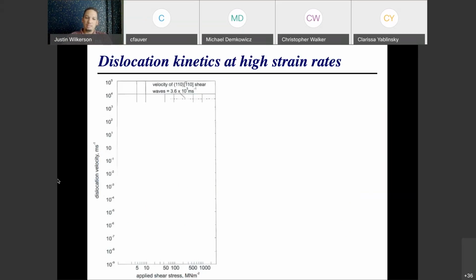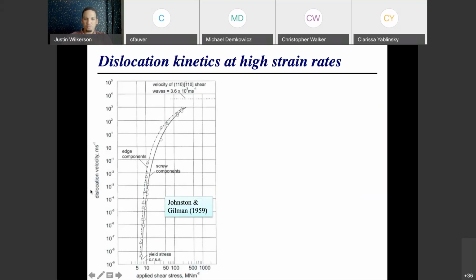So here on the x-axis, I have the resolved shear stress that's applied to the material, and on the y-axis, you'll have the velocity at which the dislocation propagates. And you can see some fairly similar trends. Again, I get a fairly linear relationship on a log-log plot for the kinetics of dislocations, and then that tends to turn over and asymptote towards the upper bound, which for dislocations is the shear wave speed of the material, the upper bound at which dislocations can propagate.